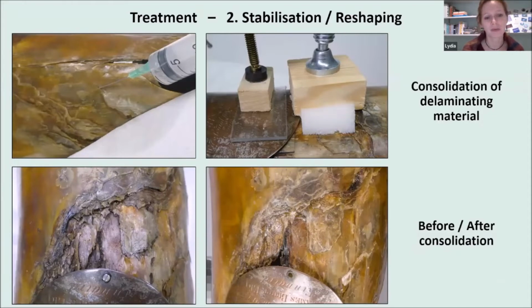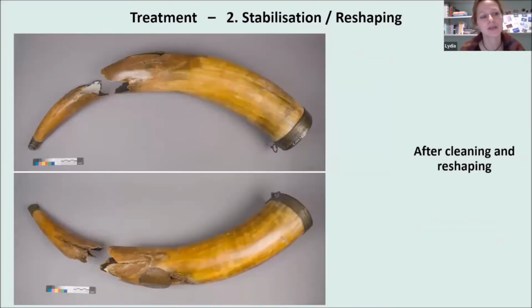After removing all the filling material from and in between the layers, I undertook the consolidation of the delaminating material and reshaped the layers which were pressed inwards in the same method as mentioned before. It took me around 2 months to reshape the horn. However, the result was worth the wait.